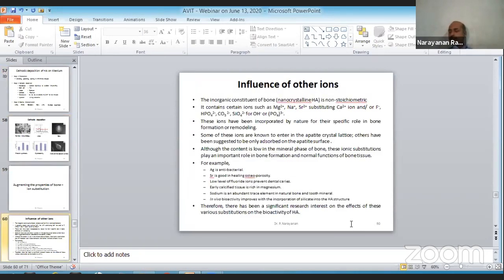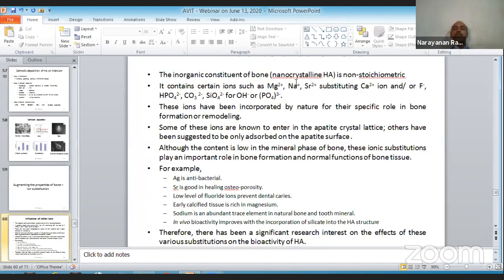Then, another study is that bone is not only made up of calcium and phosphate; it also contains other ions like magnesium, sodium, strontium, bicarbonates, and so on. Nowadays, a lot of people have very poor bone density. When you go to the doctor and there are bone defects, the bone becomes porous. The orthopedic surgeon would suggest the use of strontium granulate. In other words, the strontium granulate tablets suggested will help in filling up the bone defects, the bone pores. So the strontium ions help in better bone density. It improves the bone density.